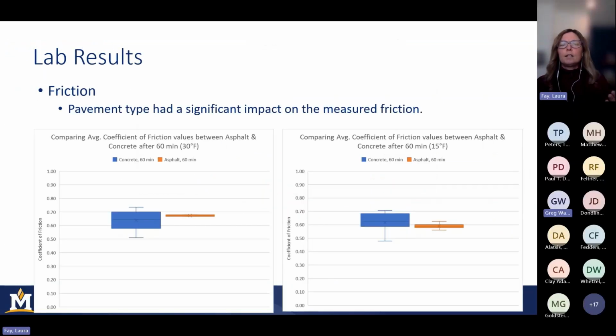But just to further validate the importance of pavement type, what you see here are after 60 minutes, these are all the results for the asphalt samples in orange. So really tight, really consistent results for both 30 and on the right-hand side, 15 degrees Fahrenheit, whereas the values from the concrete samples were much more variable. And so this might speak to the test method. And that's something that could be looked into. If we use a different data source, it may not look the same. But clearly pavement type had an influence on the results here.